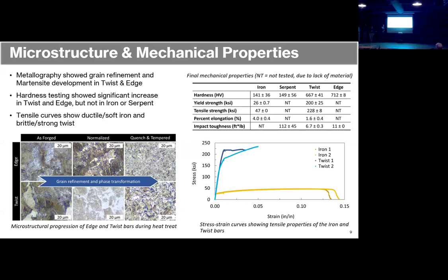We can see that the grains did get a lot smaller. So like this is a whole grain here. And as we go through the heat treatment process, they get a lot smaller. Additionally, we go from like this pearlitic ferrite structure to this martensitic structure over here. So the metallography shows that our heat treatment was successful. And then we can talk about the numbers, the mechanical properties that we tested.